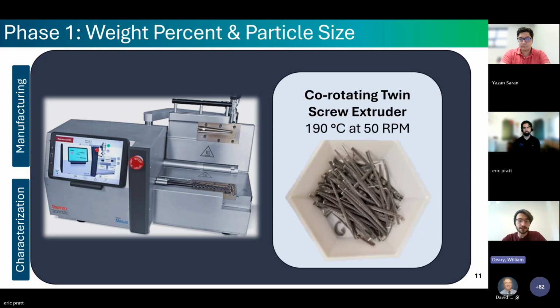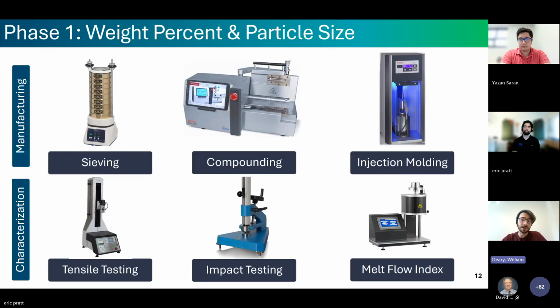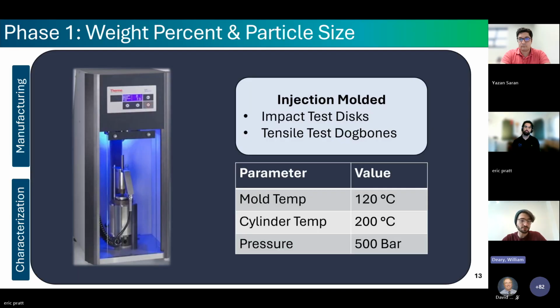Our compounded material was extruded in these continuous spaghetti-like strands, which are shown on the right, and those strands were then pelletized in preparation for injection molding. So after pelletizing, we were able to mold a variety of test specimens using a mini-jet benchtop injection molding system, and we used a cylinder temperature of 200 degrees Celsius and a mold temperature of 120 degrees Celsius. There is a two-stage pressure profile, which was 500 bar for 15 seconds, followed by 150 bar for 10 seconds, to ensure complete mold filling and fairly consistent part quality.